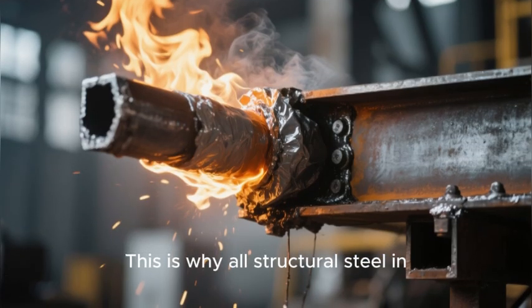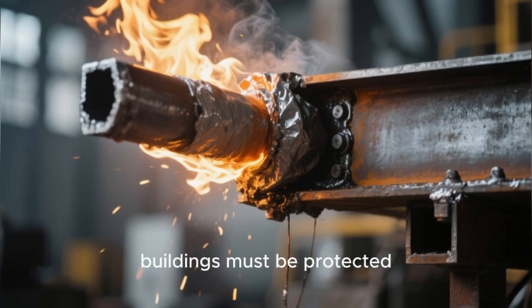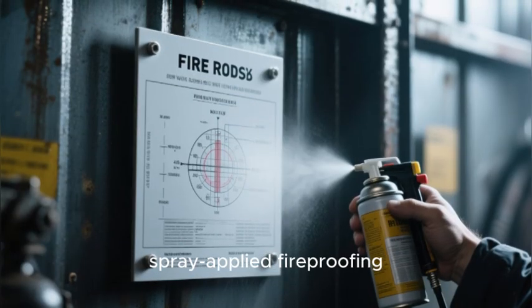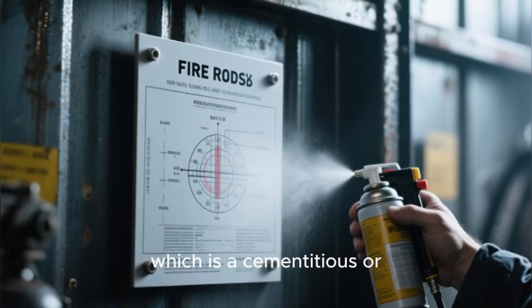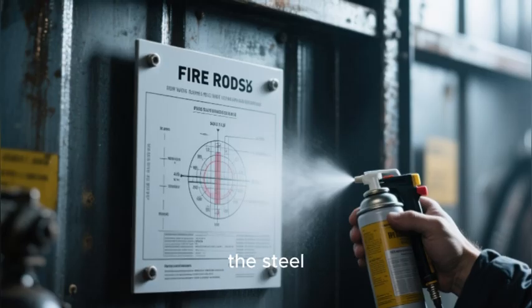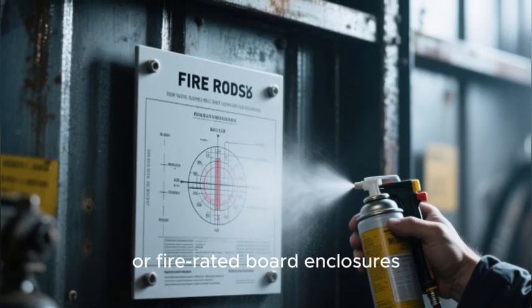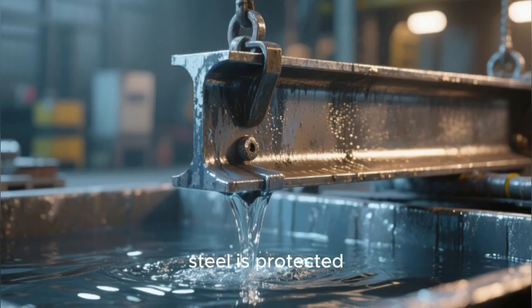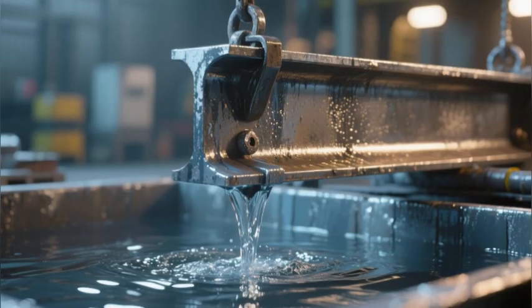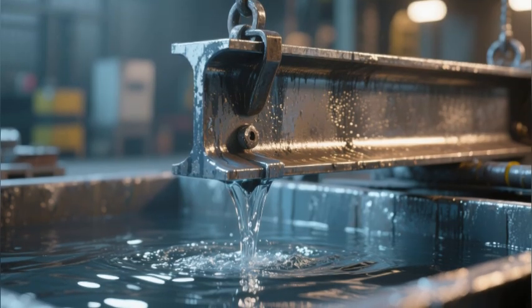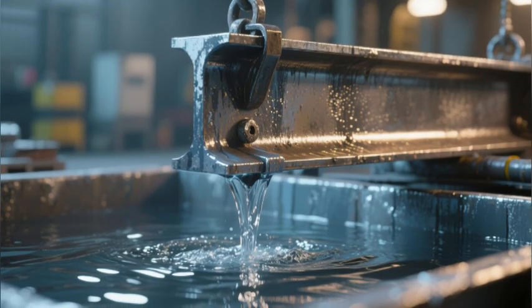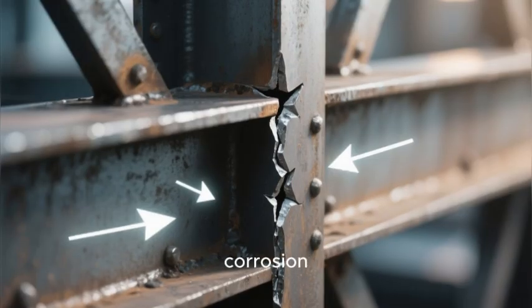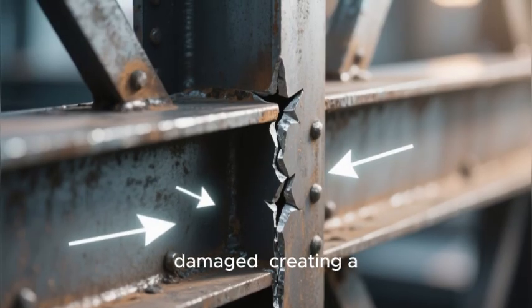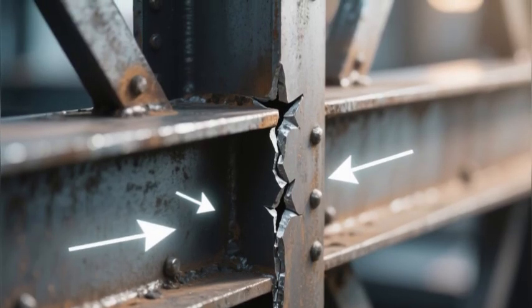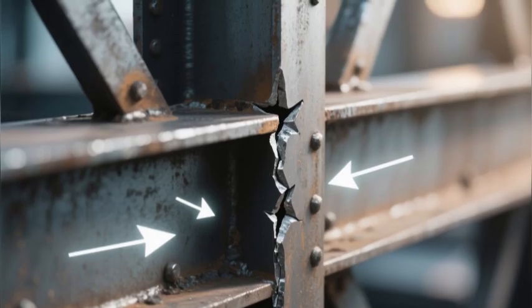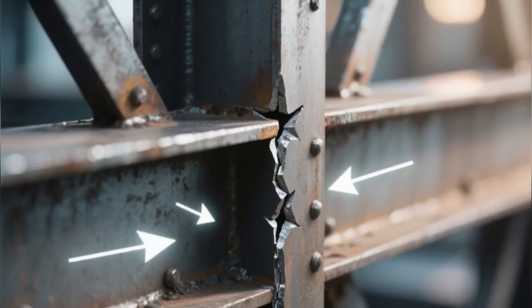This is why all structural steel in buildings must be protected. The most common methods are spray-applied fireproofing, which is a cementitious or intumescent coating that insulates the steel, or fire-rated board enclosures. Corrosion is the other great enemy. To prevent rust, steel is protected by galvanization, a coating of zinc, or sophisticated multi-coat paint systems. The pro tip for corrosion protection is to pay special attention to details like end cuts and connections, where the protective coating can be damaged, creating a point of vulnerability.